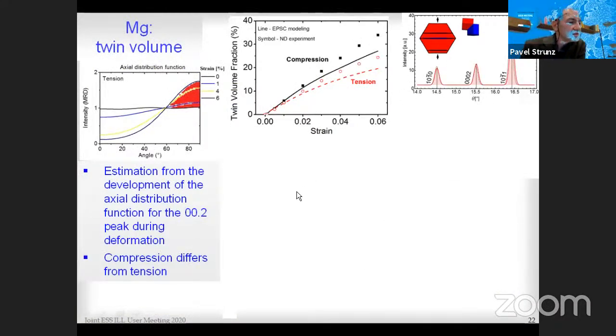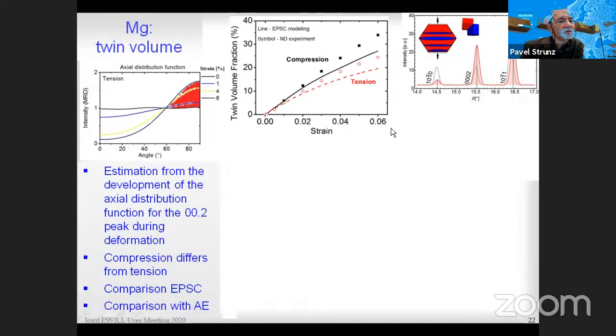First thing which we can determine is the evolution of twinned volume during the deformation. Schematically, it is shown here that we can determine it from the evolution of the 0002 peak of the hexagonal phase, of my magnesium hexagonal close-packed phase. And in fact, you determine the twinned volume from the area under this curve, from the axial distribution function for this 0002 peak. And you plot the result in dependence on strain, you get the dependence of twinned volume; for compression and for tension, they differ. And you can compare this also with the modeling of deformation mechanism.